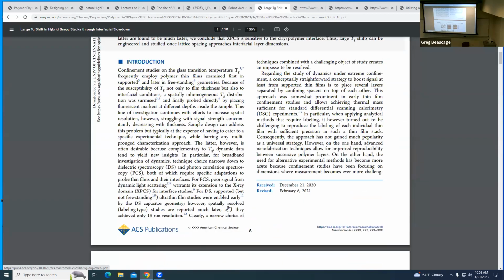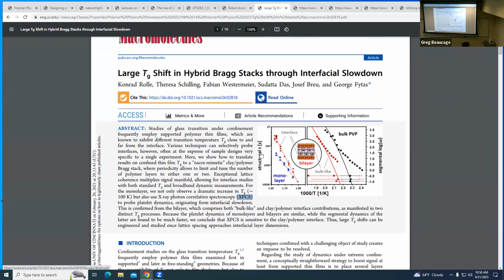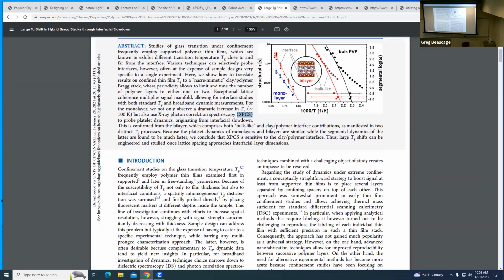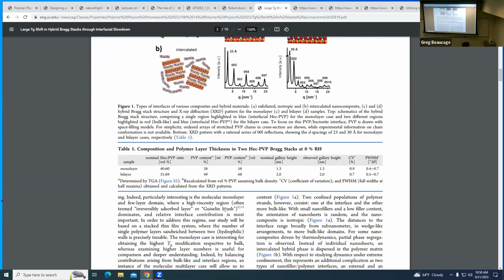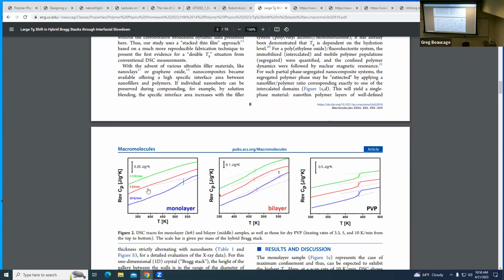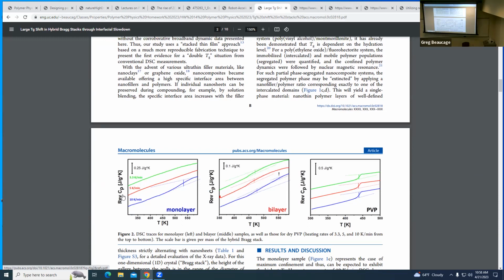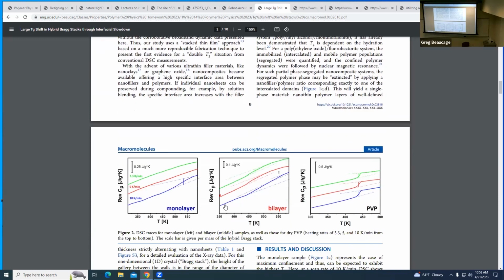So he's measured a tau with X-ray, and the tau is in the seconds, like 10 seconds, 100 seconds. And this rate is like degrees per second. So 5 K per minute, I guess. So these are on the same order as the time constants that he's getting from the other thing. So something kind of interesting that the rates here are similar to the time constants he's got. And then when it's just pure polymer, there's no rate dependence. When he puts in the clay, there's a rate dependence to the glass transition.